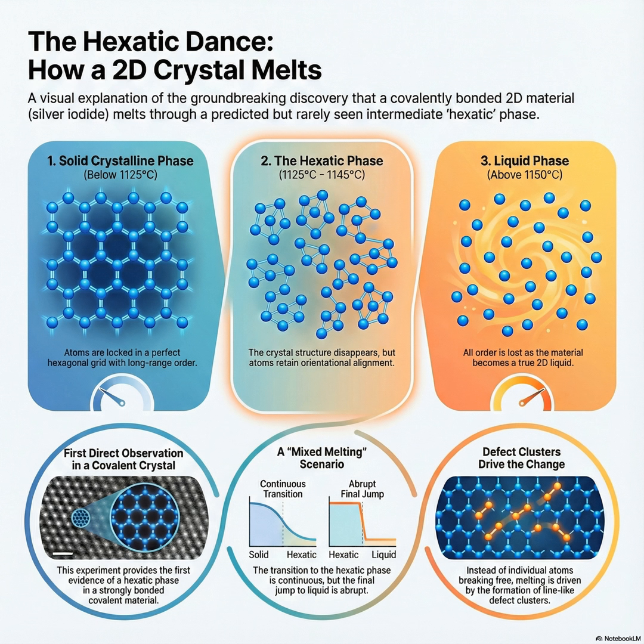But to prove it was the theoretical hexatic phase, they had to go beyond just looking. They needed mathematical proof. That's right. They had to test our dancer's analogy with hard data. They tested the two core metrics, translational order and orientational order, using what are called correlation functions. Which basically measure how far out the order extends in the material. Yes. So let's start with the translational correlation. This measures the physical spacing of the atoms. They found that in this intermediate phase, the translational correlation function decayed exponentially.